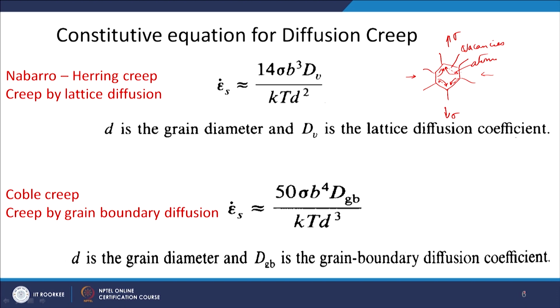Now you can see a new parameter coming here, D, where D is your grain size, the grain diameter, and D_V is of course your lattice diffusion coefficient. Because the diffusion is through the lattice, it will be dependent on the lattice diffusion, but there is also an effect of the grain size here, which was not there in the previous equation. So you can see again how we are trying to linearize the equation to get this empirical relationship, because now there will be an effect of grain size. So grain diameter is coming into the picture.